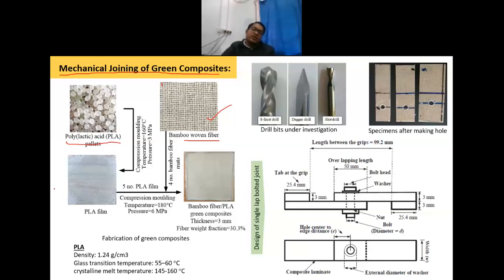Okay, so what we have done, first we have converted these PLA pellets into PLA film by using the compression molding. We have applied the required amount of compression pressure and temperature, so that we can convert these PLA pellets into PLA film. Then we have created 5 PLA films, and we have taken 4 bamboo fiber mats, and then we have stacked them alternately in the compression mold. First we have placed this PLA film, then the woven fiber mat, then PLA film, then again woven fiber mat. Like this way we have stacked it.